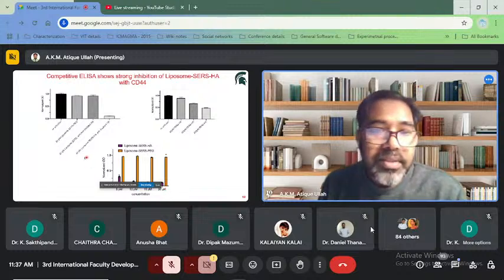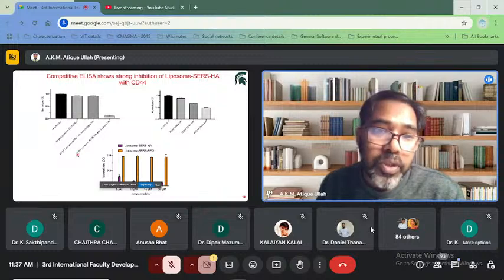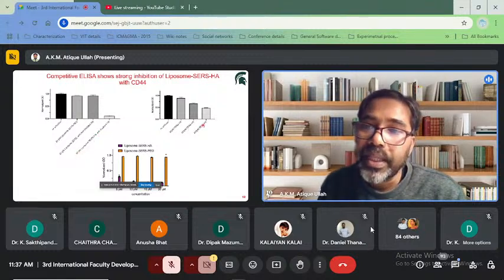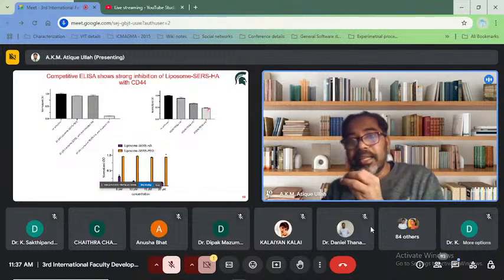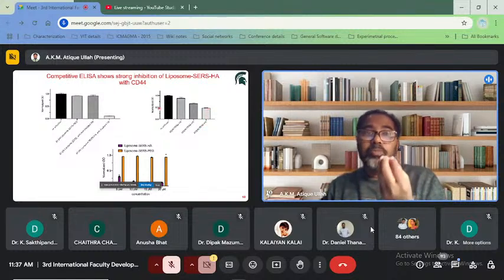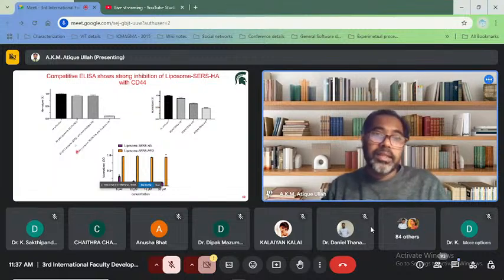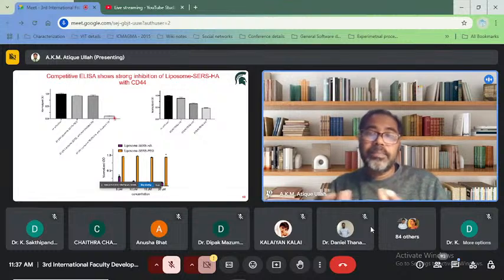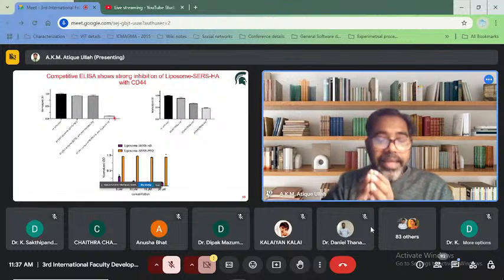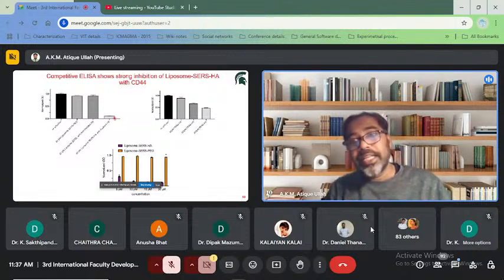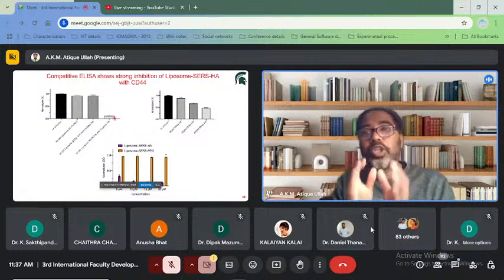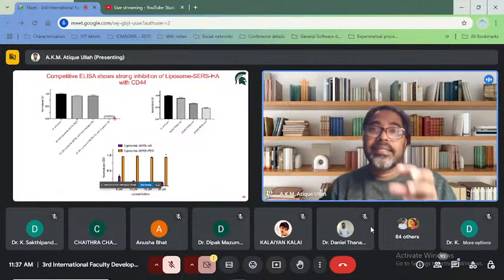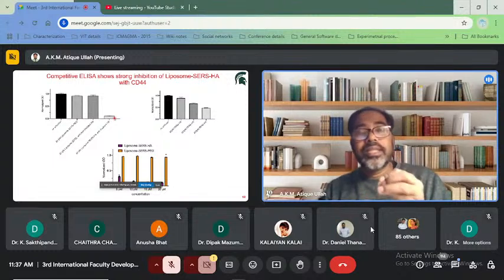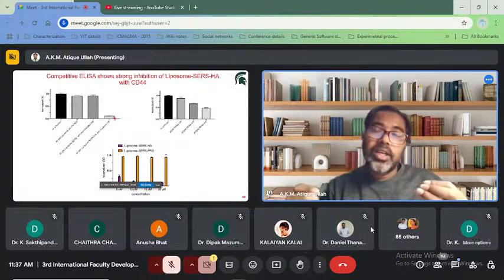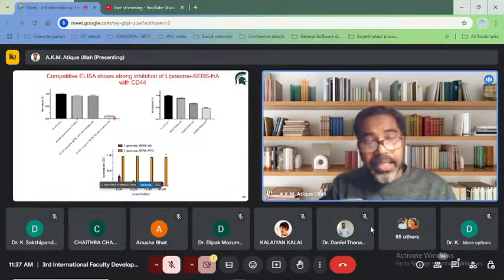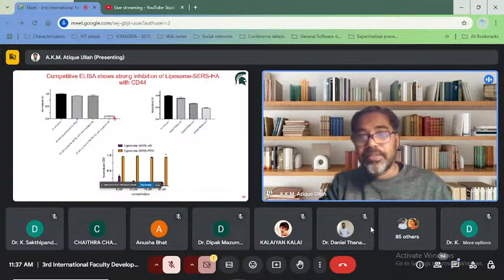And you can see, suppose this is the 20 picomolar and this is the 250 picomolar HA. You can see the free HA, the intensity decreased to 0.5, but with only 20 picomolar, the intensity decreased to almost 0.2. That means our Liposome-SERS-HA can bind more strongly than the free HA. So we can conclude that Liposome-SERS-HA can selectively bind with the CD44, which will help us to distinguish or differentiate the cancer cells or cancer which has the overexpression of the CD44.